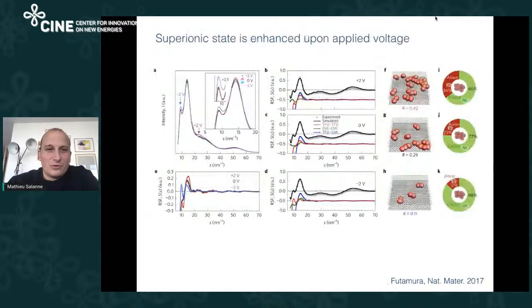Then, if I continue with this experimental study, you can see that in fact the structure is changing depending on the potential you apply. And what happens is, if you focus on the picture on the right, you have some arrangement of ions that are close by inside the pore, and you see that in the middle, when you have 0 volt, you have only a few ions that are close by, but if you increase the potential, there start to be a lot of them. On the contrary, if you have a negative potential, then you remove some anions from the system and you start to lose this arrangement.